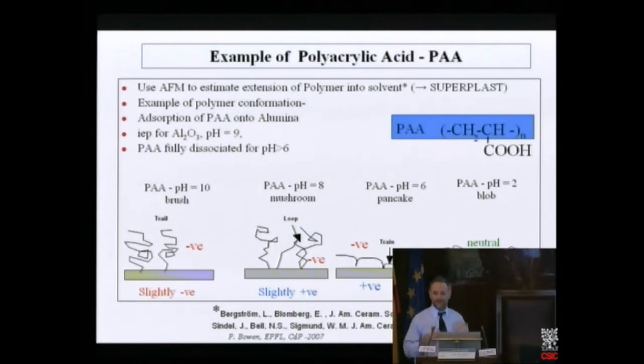It adsorbs to the surface. It'd rather be at the interface than in water. If particles come together, the polymer-polymer interaction is much more preferable than polymer-water, so they just stick together. So you're not only not dispersing it, even if you have an adsorbed layer. The polymer still has to like the solvent.